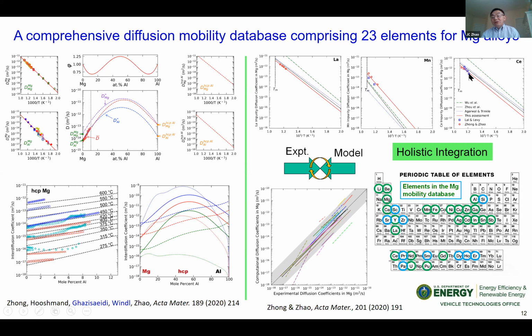You can see that because the temperature range is so small, you can't get activation energies. For example, if you use the activation energy from this square data below, it will be far away from the computed data. So because we did a lot of comparison, we trust the computed activation energy, and then we use the experimental data to fit the D sub 0. That's how we can get more reliable data. Holistically integrating both the experiment and the computation gets the best out of both.